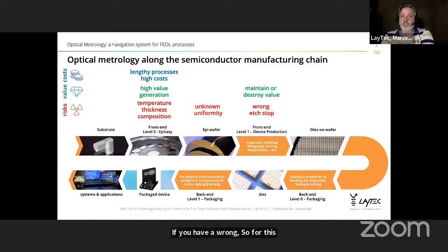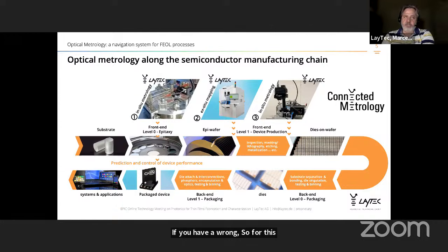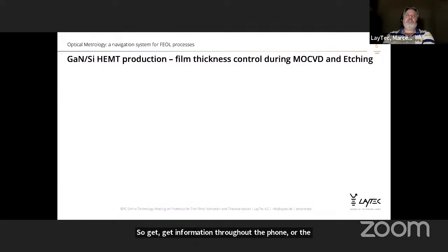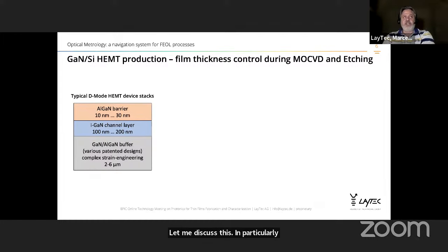So for this reason, to control all of these steps, we propose and implement our in-situ methodology and ex-situ mapping: in-situ methodology at the level of the front-end epitaxy, ex-situ mapping between different epitaxy steps, and again in-situ methodology during etching. And this is what we propose as a concept of connected metrology. So gather information throughout the front-end line of the processes in order to better understand what is happening to your wafers. And let me discuss this in particular with an example of GaN-on-Si production, where we show how it is possible to control film thickness to a very high accuracy during MOCVD and etching.